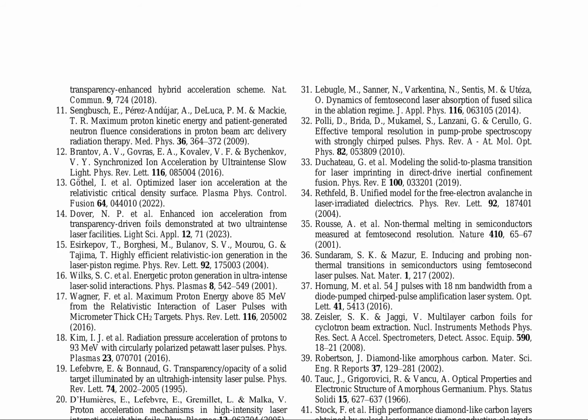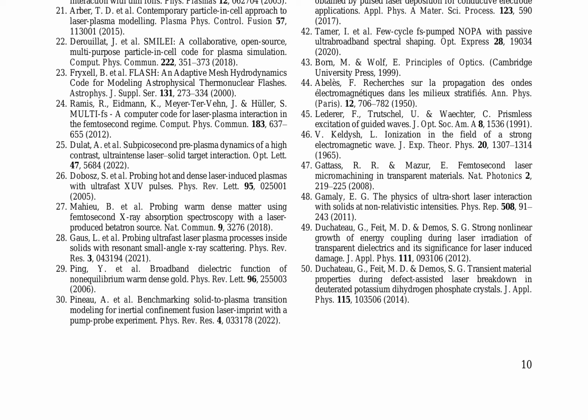The model is validated by comparing simulations with experimental data on fused silica, accurately predicting observed damage patterns and identifying primary damage mechanisms. The study also explores the role of defects, pulse duration, and intensity on damage, showing that shorter pulses lead to more localized damage and higher intensities result in more extensive damage. This work presents a novel approach for understanding femtosecond laser-induced damage, providing a comprehensive framework for simulating the entire damage process.